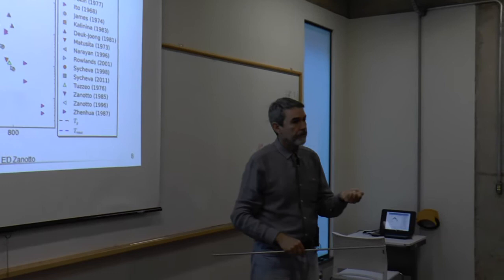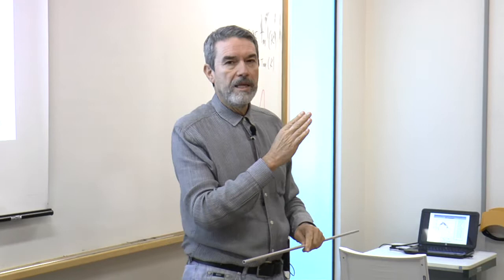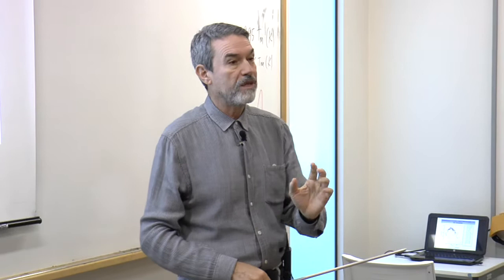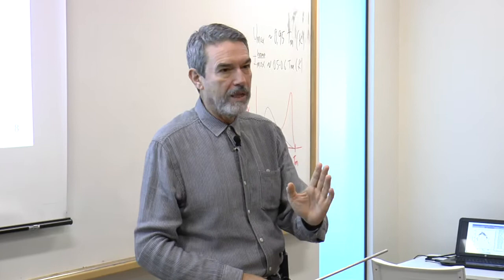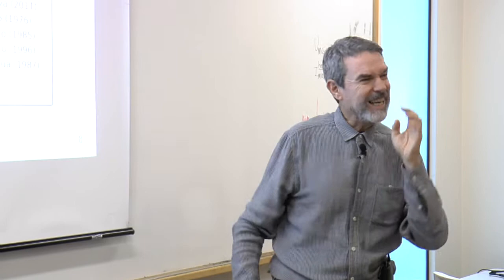And another difficult problem is that one wants to produce a stoichiometric lithium disilicate, exactly lithium disilicate, and it's almost impossible. There's some loss of lithium, there are impurities in the chemicals, so you are to one side or the other side, let's say 0.1, 0.2, 0.3% to one side of the composition, lithia rich or lithia poor. So none of these glasses are exactly lithium disilicate. They're more or less lithium disilicate, and they have different degrees of impurities. Also, there are errors in the actual measurements. It's all embedded in these curves.